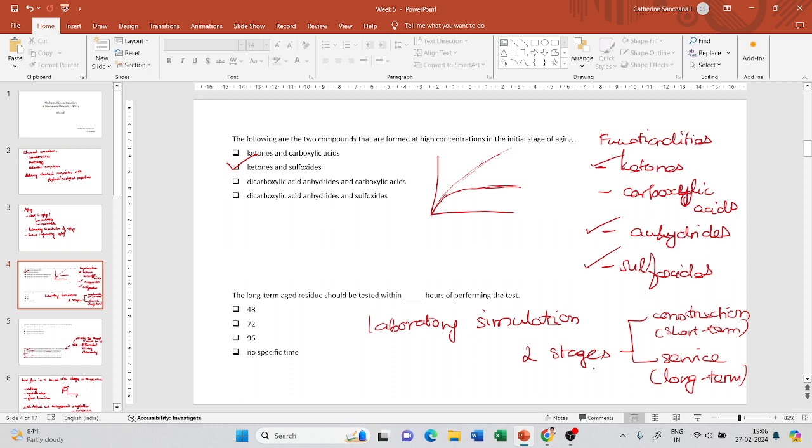relate any results that you get to the field, because the aging that happens in the field is a lot more different, as it has additional factors. For one reason, you have mixed your bitumen with aggregates, which will have a major impact on aging. Some of the lighter fractions could be absorbed onto the aggregates for one kind of bitumen, while for another bitumen, maybe it is not.